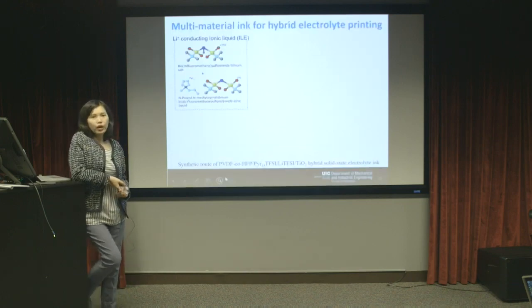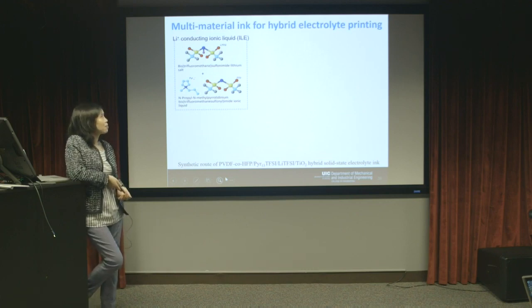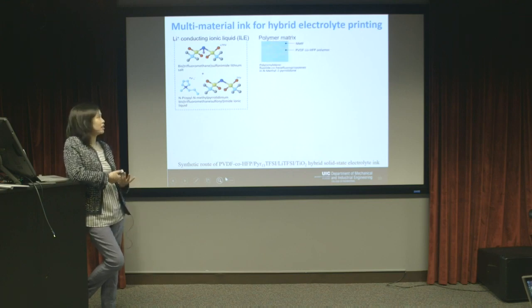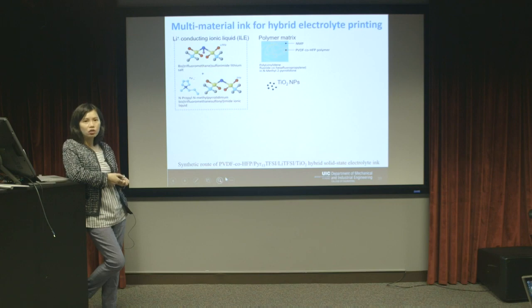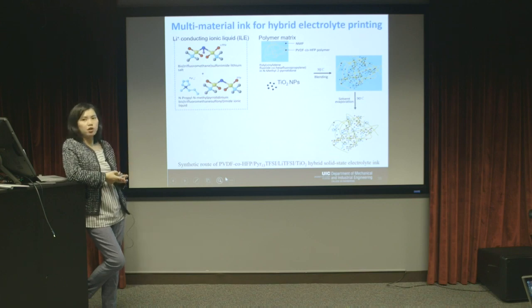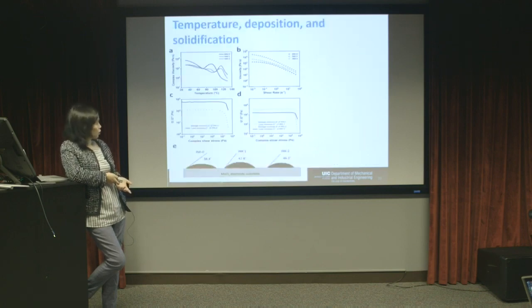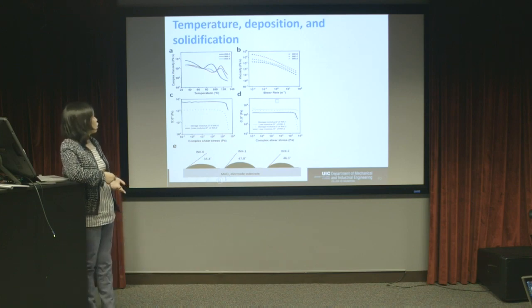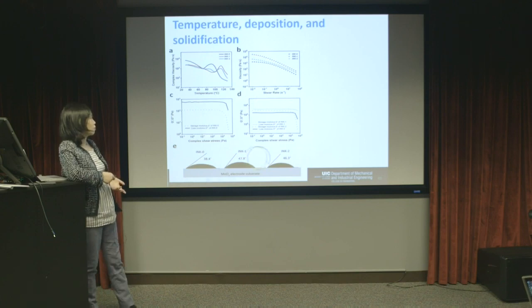We collaborated with another group at UIC and developed a new ink, a hybrid electrolyte ink. This ink is a porous polymer matrix, and it contains the lithium ion conducting ionic liquid inside of it. We also added some titanium oxide nanoparticles into it to modify its viscosity and its conducting properties. And we can adjust the nozzle temperature and the platform temperature to print it, solidify it and stack it on the platform. By controlling the temperature, we can achieve different viscosities and also different moduli.